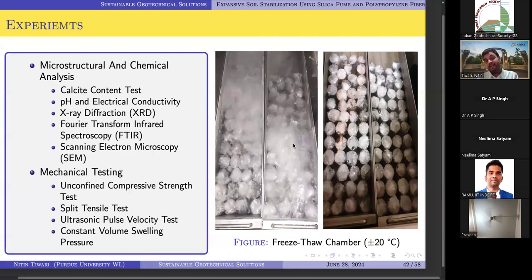Just a day before the study, I had a meeting with TRB, and in TRB we were talking about this test improvement. So soon you people will hear that ASTM will have a new protocol for freezing thawing analysis. So we go from plus 20 degrees Celsius to minus 20 degrees Celsius so that we can understand, if there is a different freezing thawing cycle, what will be the impact on the infrastructure.